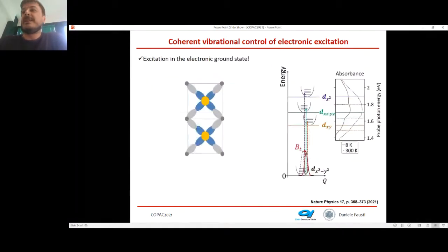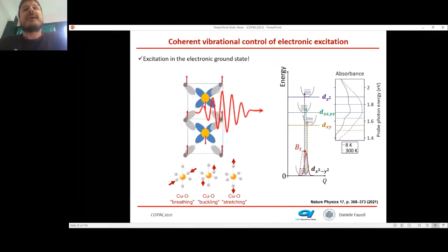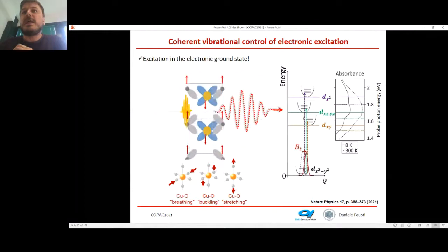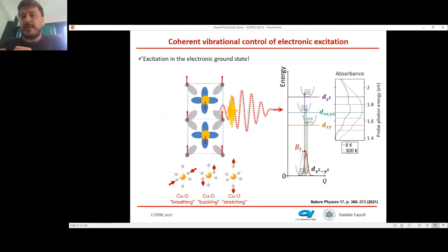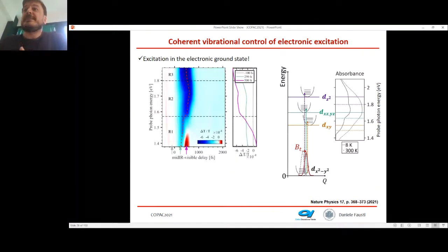So the idea of this experiment was relatively simple. We said, okay, if phonons make an electronic transition allowed, can I resonantly drive the structure so that I move the ions around? And will I be able, by doing this, to change the electronic absorption of one single atom? It turns out that the results were more interesting than we expected, because if you photoexcite the system with high energy photons, basically you never win against the entropy. So what your photoexcitation does is always increase the disorder. And if you increase the disorder, the thermal excitation of the structure, then you always increase the absorption of these electronic transitions, which are phonon-assisted.